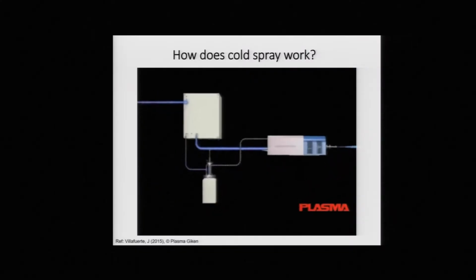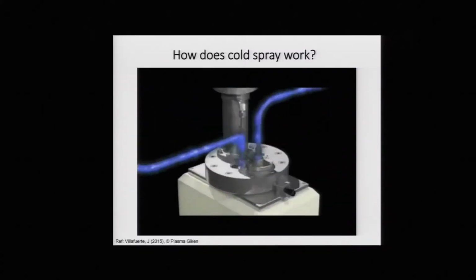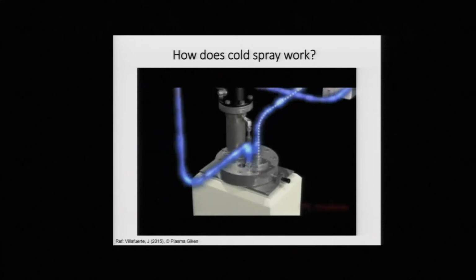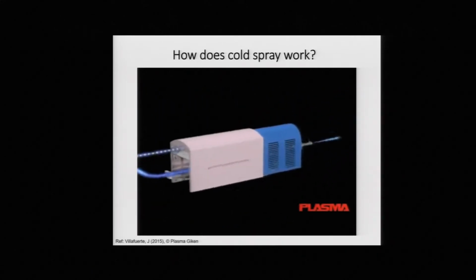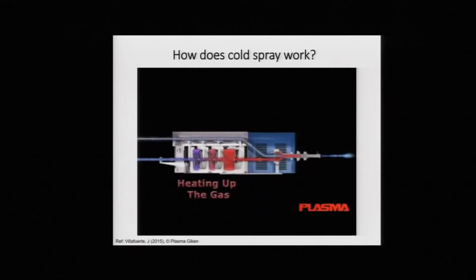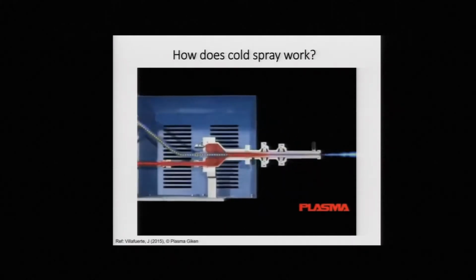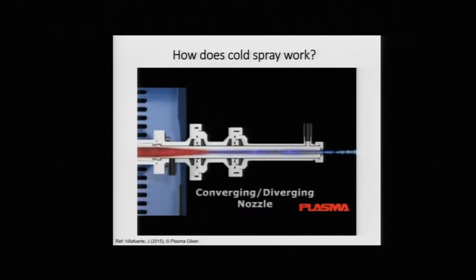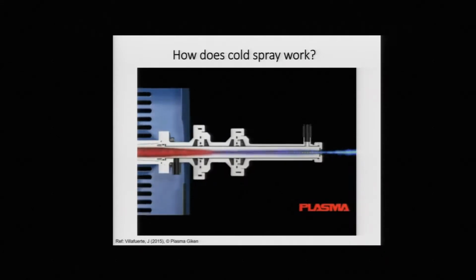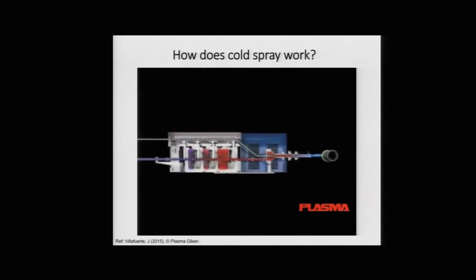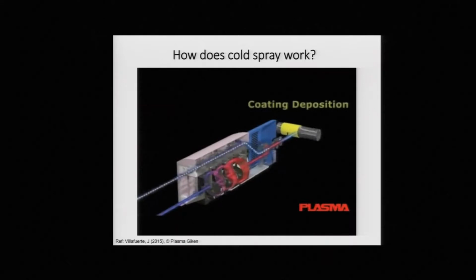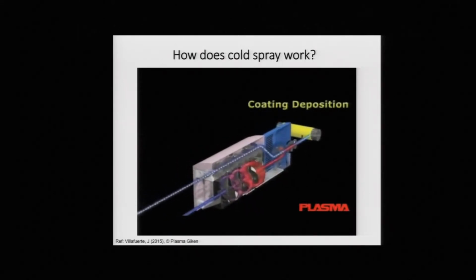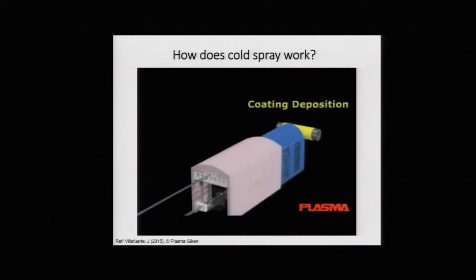The gas that's going directly to the powder feeder will allow the powder to be injected into that gas stream. Once it reaches the nozzle, it recombines with the heated gas and can then go through the nozzle and achieve supersonic velocities. The particles coming out of this nozzle then impact the part and can create a coating.